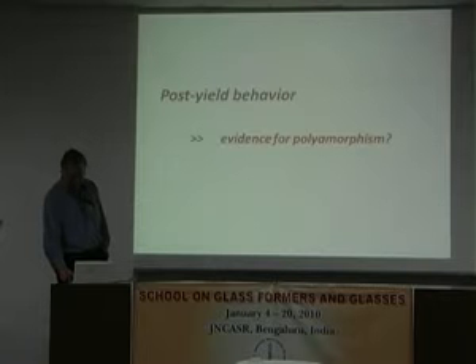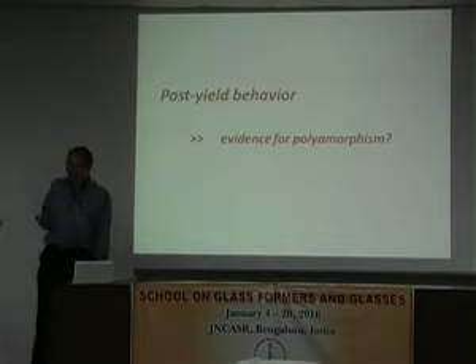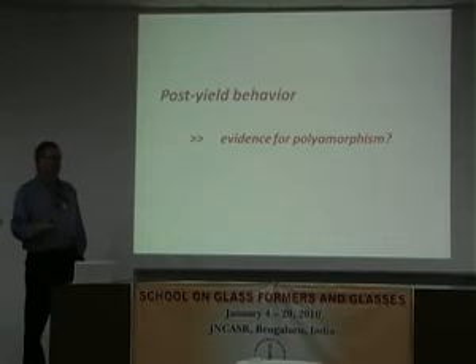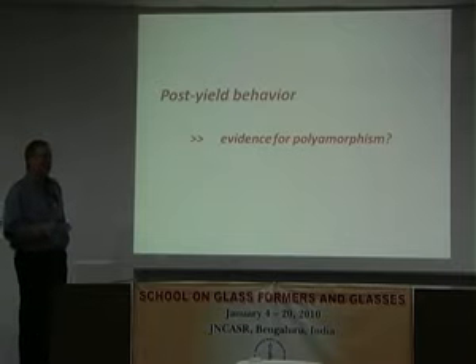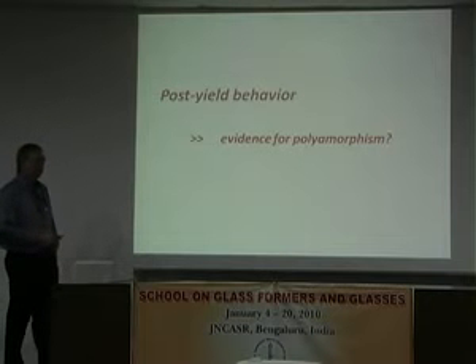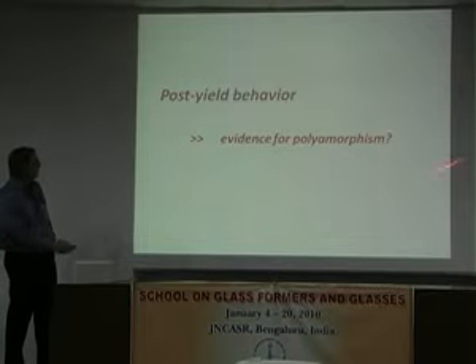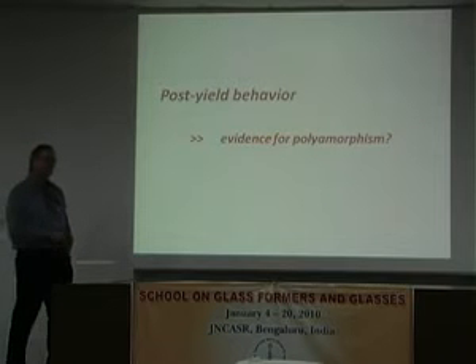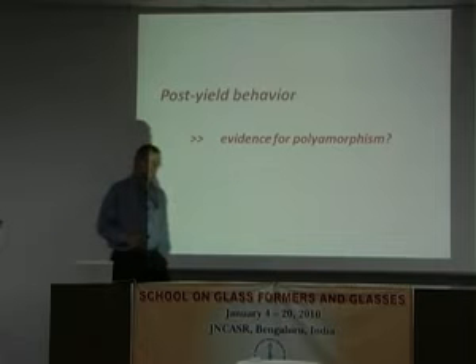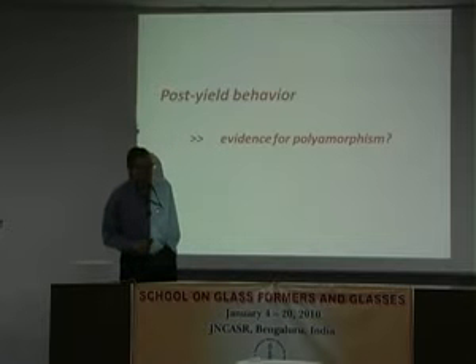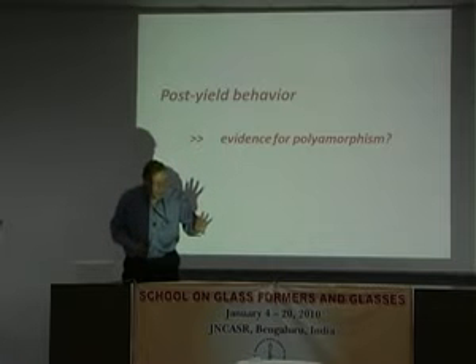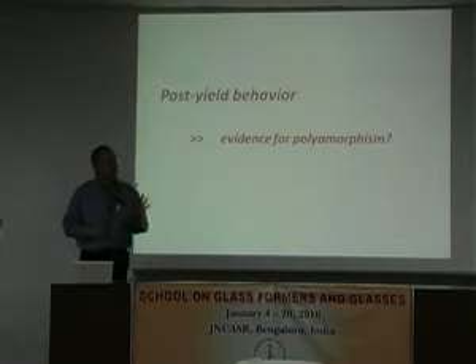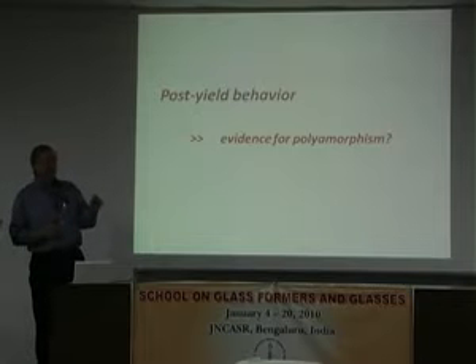We didn't do the dilatometry in yield because then we would have had to take out the sample, and it took a week to load a sample. But here's the post-yield behavior. Does it give evidence for polyamorphism? Yeah. So below yield, locally when you apply the stress, it's responding elastically. Does not respond elastically. It responds viscoelastically, non-linearly viscoelastically.